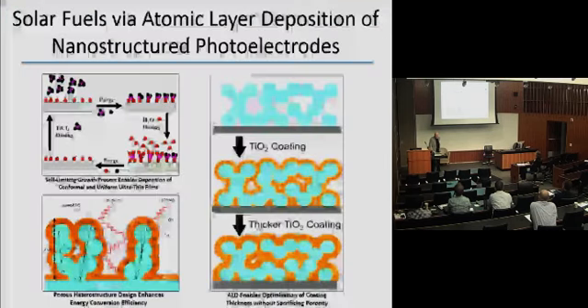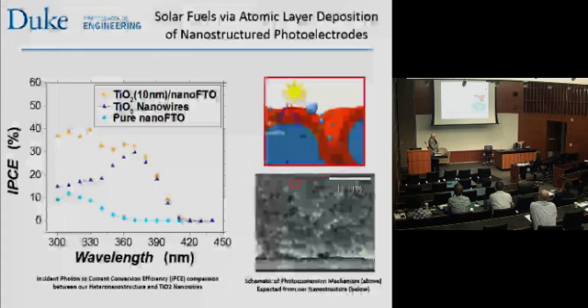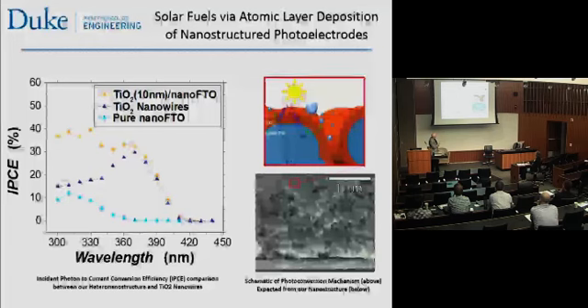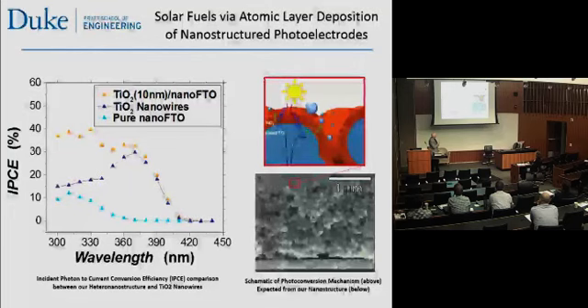Let me skip over that and just end the discussion of the actual results with this. So I mentioned the atomic layer deposition, and I said all this verbally, but just to show this nanostructure, all these nanoparticles are coated with this atomic layer deposition of TiO2 in order to give us a very high quality solar fuels system. So we can basically split water and convert water to hydrogen and oxygen. And you can see the way that's doing that. I won't go into the details of the process, but you see the old materials are shown here, and this is their absorption in wavelength. And if we look at the new material that has been developed, it actually does better than both the other materials in this low wavelength area. So it's found a way to combine the best of both worlds in terms of the nanostructure and the energy conversion, or the photon conversion as it goes into the material.